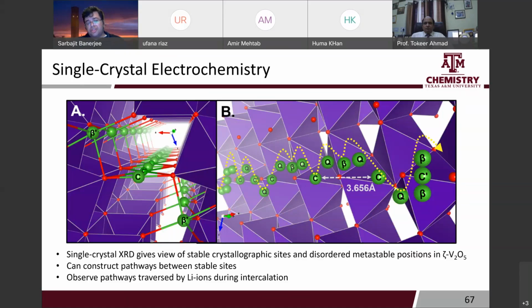Right. So we measure the same single crystal at different extents of lithiation. This is not particularly fast because we have to acquire single crystal diffraction at each extent of lithiation, but we can get a very detailed pathway at every point. I think I understand where your confusion might be coming from. Again, we're lithiating an intact single crystal. We're not making a single crystal of lithium V2O5.